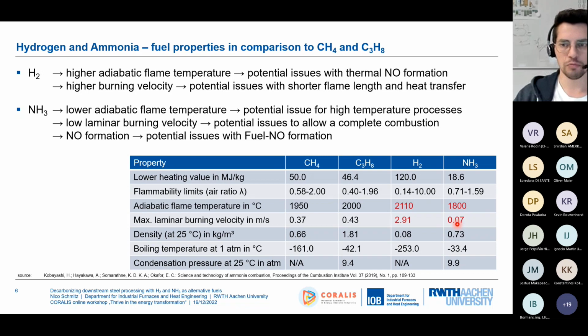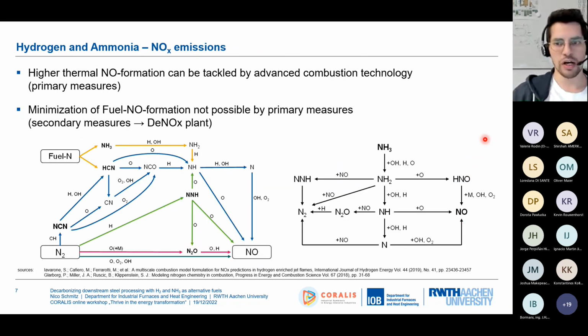I want to say a few words about NOx emissions here, because for our plants, it's not typical that we have DeNOx systems. Normally, we only work with primary measures to minimize our NOx emissions. For hydrogen systems, the higher thermal NO formation is the first issue. You see down there in blue this path of NO formation, which is mainly the attack of oxygen radicals or hydrogen radicals on the molecular nitrogen, leading to NO formation. This is mainly dependent on the residence time of the gases at high temperatures.